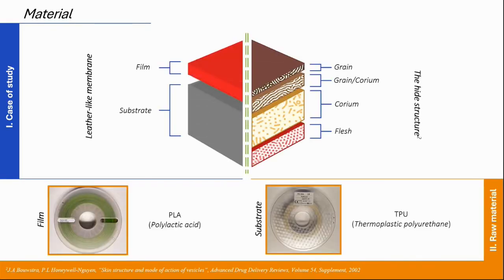The structure, schematized in the right picture, is split in tanneries to obtain usable sections for a good quality leather. The two first layers, grain and corium, define the top grain, a high-quality split. The grain near the surface has a compact appearance and has thinner collagen fibers, while the corium under the grain is characterized by thick fibers. To recreate a leather-like membrane that mimics the structure of the hide, we substitute the top grain's layers with a two-layer membrane that resembles the structure of the top grain. This allows us to define a clear subdivision between the film grain and the foundation corium.